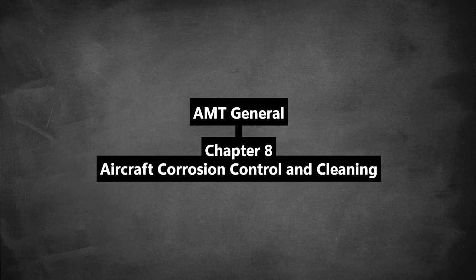You often can't fully replicate these original factory finishes in the field, but understanding them helps with proper maintenance and partial restoration. Surface preparation is key for any finish. For steel, that means removing all dirt, oil, grease, oxides, moisture. It can be mechanical: wire brush, steel wool, sandblasting, but chemical cleaning is often preferred as it doesn't remove base metal. Pickling in acid removes scale before plating.